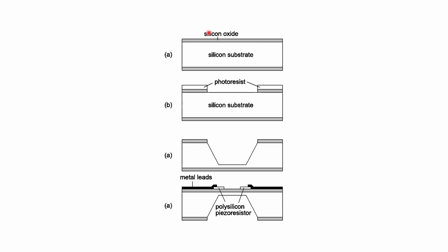Here's one example process where you can use this to make a pressure sensor. You have a silicon substrate, grow oxide on both sides. Use photoresist to pattern the oxide on one side. Oxide is a good resistant to the KOH or EDP etching. And as long as the etching does not completely consume the oxide, you can form a deep enough cavity. Here you don't want to form an inverted pyramid, but you want this to be wide enough that you have a membrane. The membrane depth can be controlled in theory.